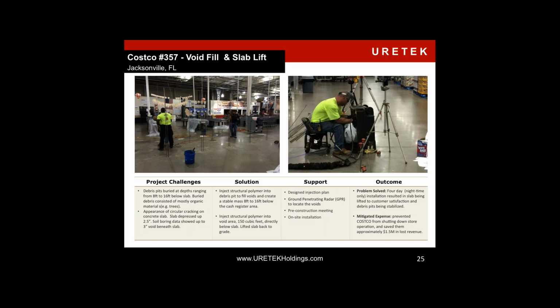An injection plan was put together. Here you can see the tubes being put in place, because it was determined that the soils were weak at the 8 and 16 foot mark. So materials were injected. Here the injection process is going on, and again, laser measurements can determine if there's even a millimeter of movement. So that's the kind of controls that are placed on this. The materials injected, soils were stabilized, and they were able to work at night when the customers weren't there, so Costco did not experience any downtime with this. And no sooner were we finished, we were able to open it right back up to them.